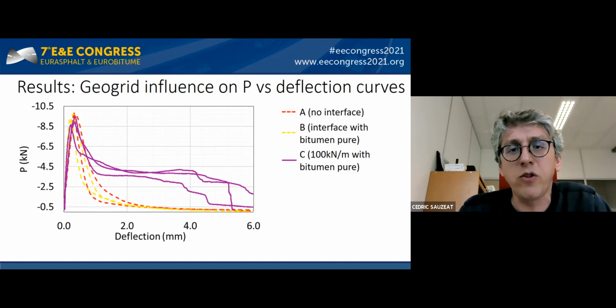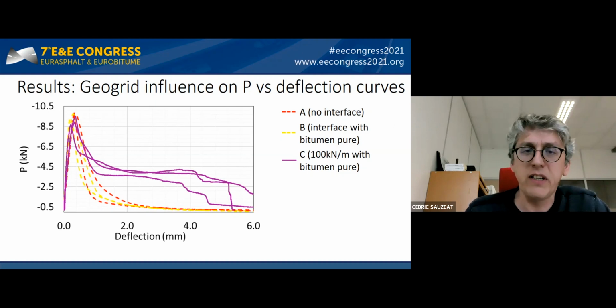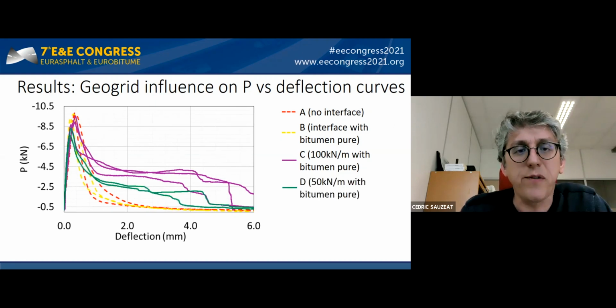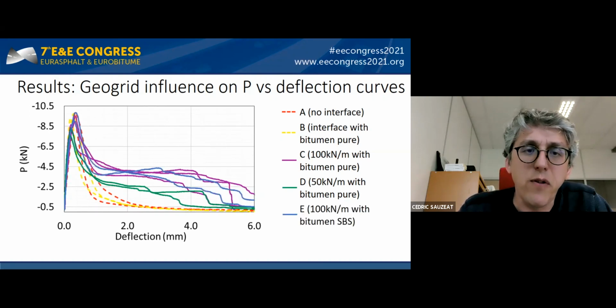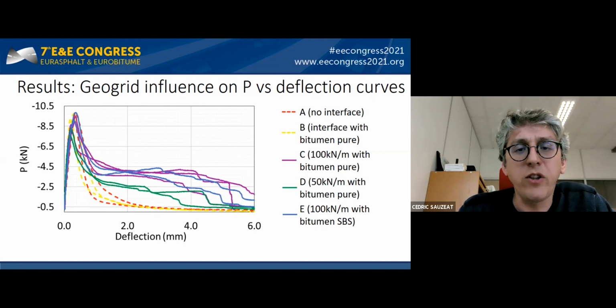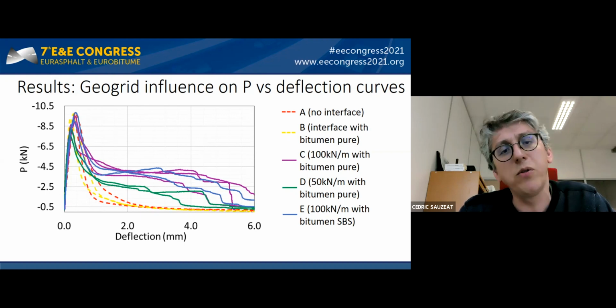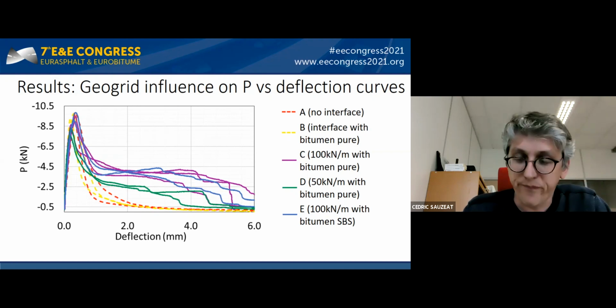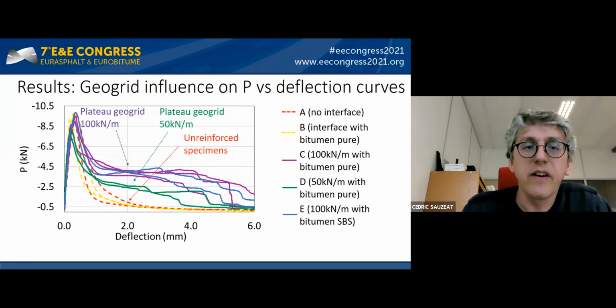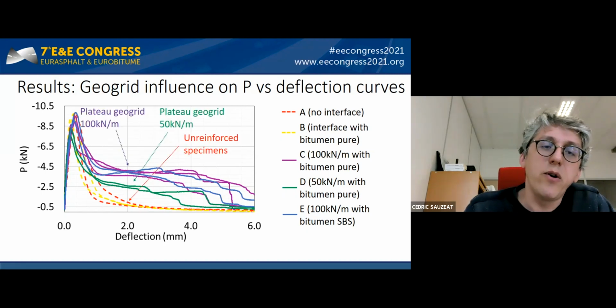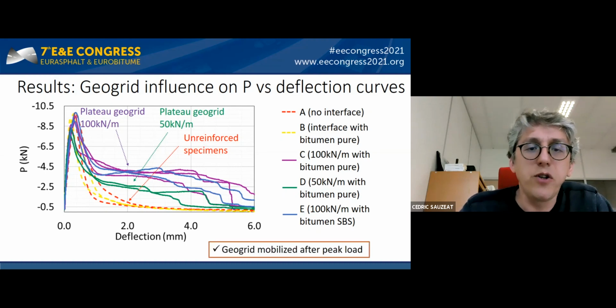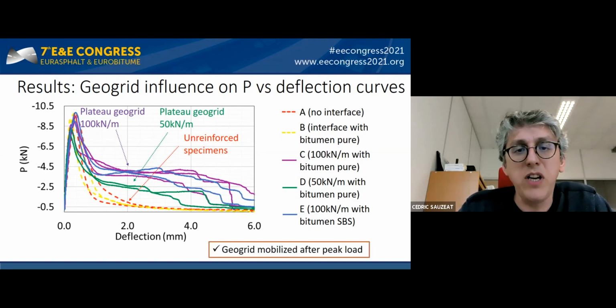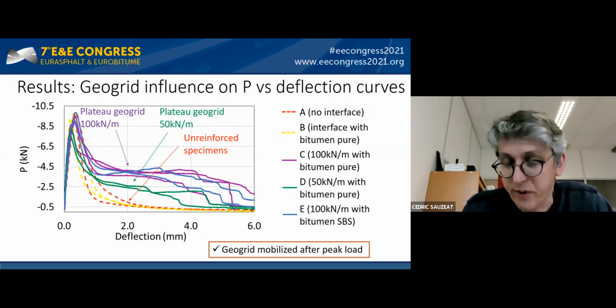The same result, but with the reinforced specimen with a 100 kilonewton per meter geogrid. The same result for the 50 kilonewton per meter geogrid, and the same result for the 100 kilonewton per meter geogrid, but using polymer modified bitumen. You can see the difference: there are plateaus that appear after the peak, and the geogrid is only mobilized after peak load.